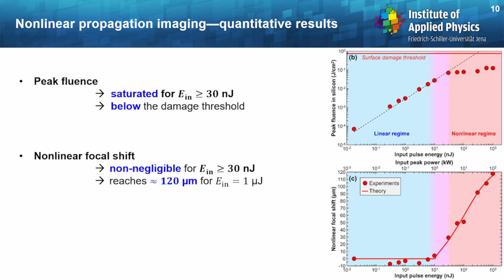And then there is another interesting parameter to look at, which is the nonlinear focal shift, so how the focus shifts from the linear position. And this is represented here, again, as a function of the input pulse energy. And one can see that the nonlinear focal shift becomes non-negligible for input pulse energies higher than 30 nanojoule. And it may reach around 120 micron for input pulse energies around 1 microjoule.